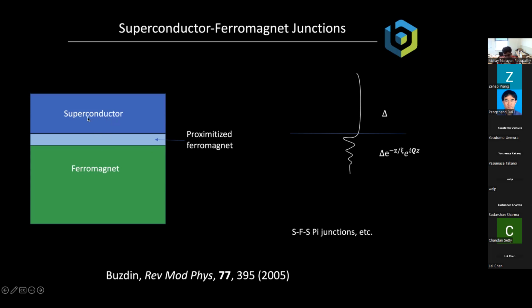I would say that this kind of research always ran into a little bit of problem because the way you made these kinds of samples was you evaporated a ferromagnet and then you perhaps oxidize the interface and then put in a superconductor. And when you grow materials like this by thin film growth, it's always very difficult to get a beautiful interface.